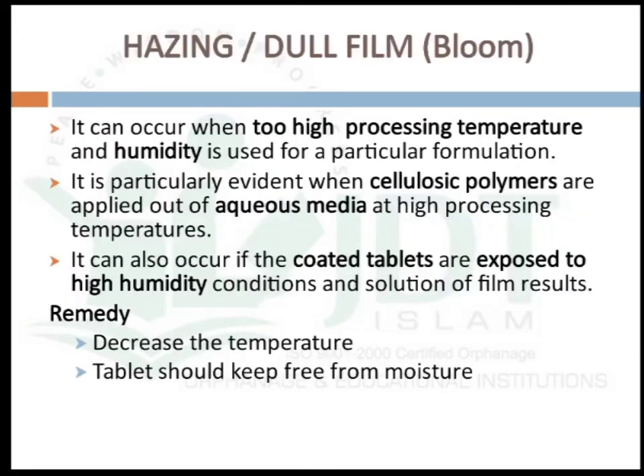The next defect is hazing or dull film. It occurs when too high processing temperature and humidity are used for a particular formulation. It is particularly evident when cellulosic polymers are applied from aqueous media at high processing temperatures. It also occurs if the coated tablets are exposed to high humidity conditions causing dissolution of the film. This can be rectified by reducing the drying temperature and keeping tablets free from moisture.